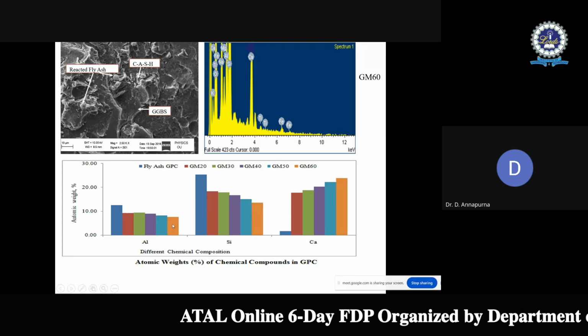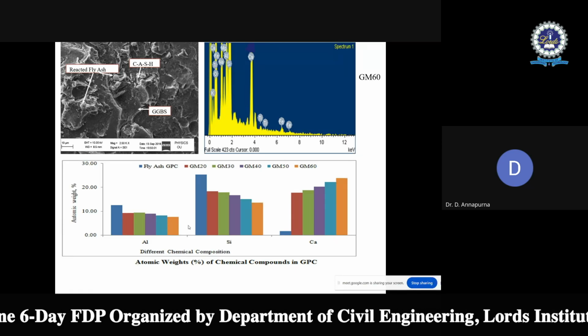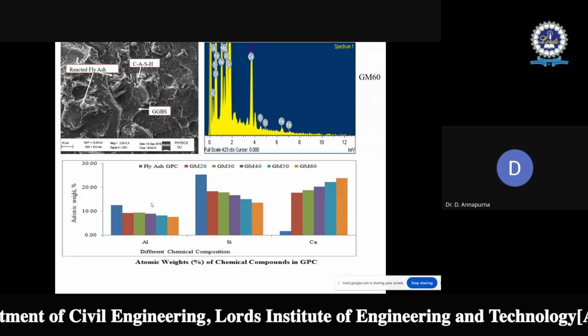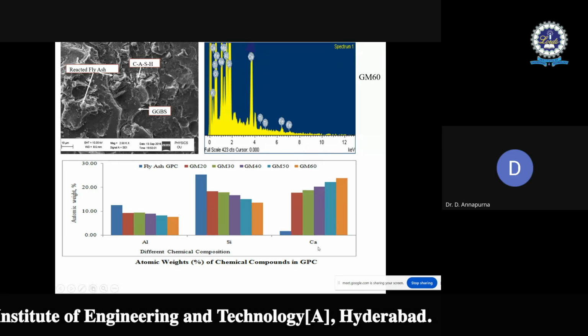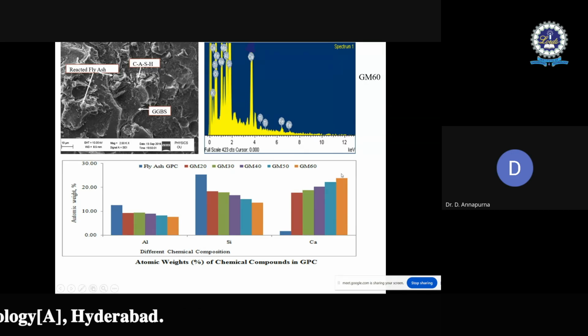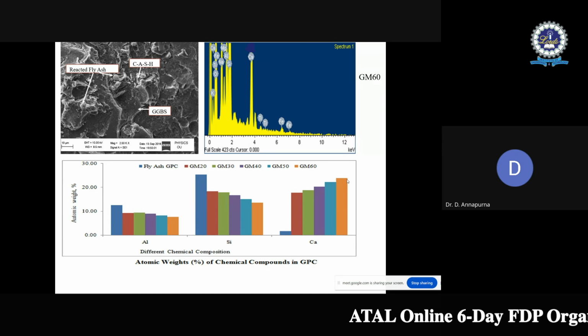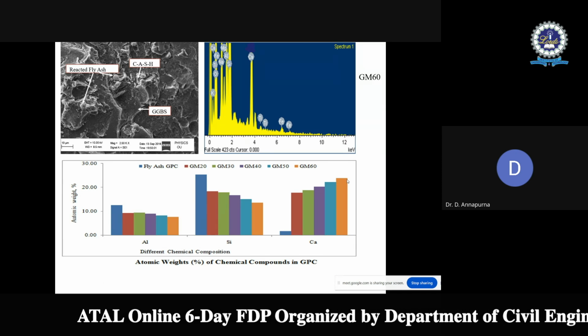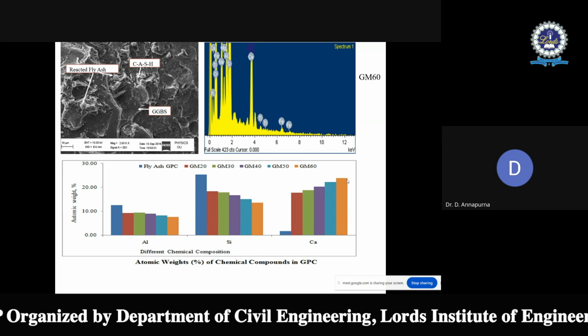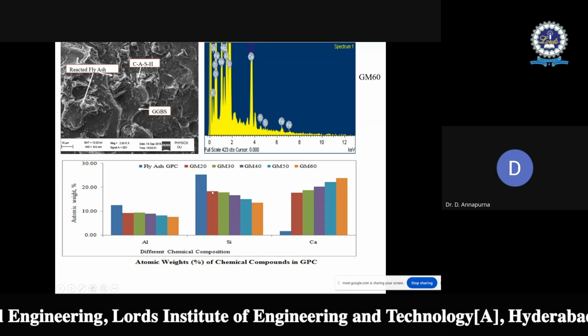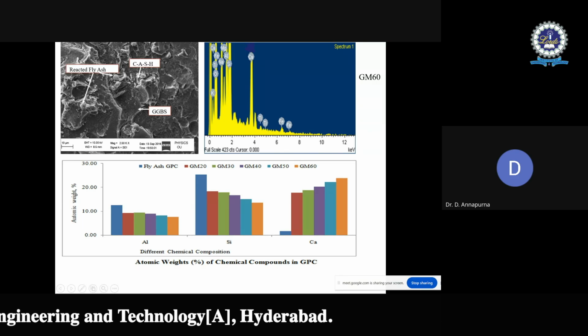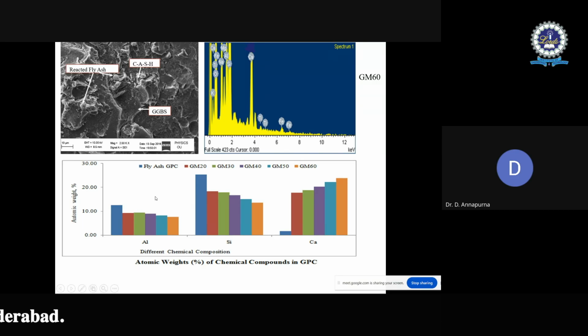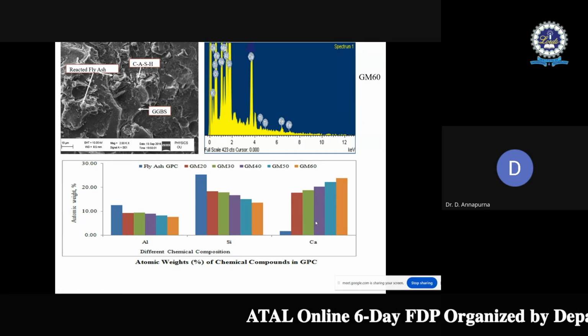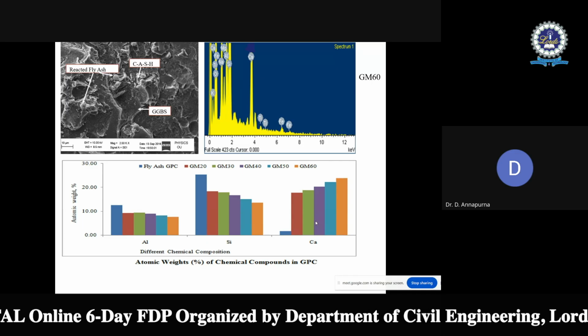All these GM20 to GM60 grades have a silica by alumina ratio more than 1.65. Even GM60, which has the highest amount of GGBS, still maintains a silica by alumina ratio of more than 1.65. More than 1.65 confirms the presence of geopolymer product, that is sodium aluminate silicate hydrate gel. Along with that, some traces of calcium aluminate silicate hydrate gel are also confirmed through the calcium by silicate ratio. When we take the ratio of calcium by silicate, it ranges from 0.97 to 1.7, confirming calcium aluminate silicate hydrate.